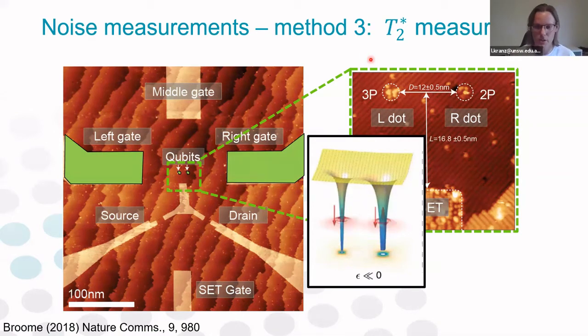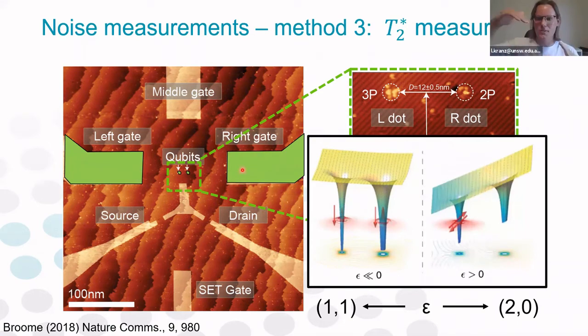The donor qubits provide a very strong, very sharp confinement potential, schematically shown here, so that if we load 1 electron on each qubit, the wave functions are pretty small, with a 2 or 3 nanometer Bohr radius, so they can be understood as independent wave functions. However, if we use gate voltages on the opposing gates, we can create a tilt in the electrochemical potential. This tilt we call detuning, because we're detuning the energy levels of the 2 dots with respect to each other. By controlling this detuning, we can go to the 0-2 charge configuration, where we force both electrons into the same quantum dot. We can also go somewhere in between, where we control the overlap between the electron wave functions, which gives us some finite value of exchange interaction.